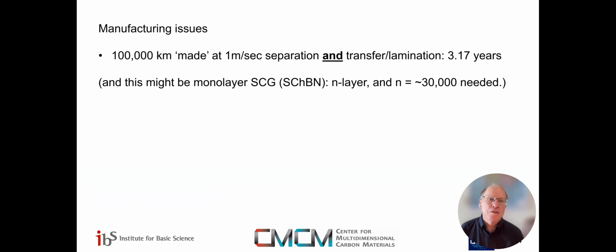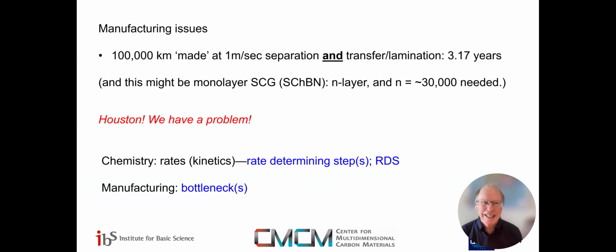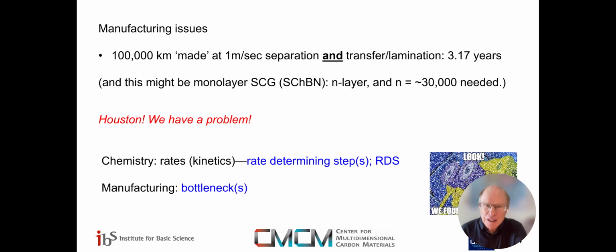So we have manufacturing issues, and if we were to consider that we make this material at a meter per second and transfer and lamination works, this would be 3.17 years. This is only monolayer single crystal graphene. It's not the 30,000 layers that we need. Houston, we have a problem. So chemists refer to the rate determining step in manufacturing terminology like bottlenecks are used. And my face is in the way, but this little guy says, look, we found a bottleneck.